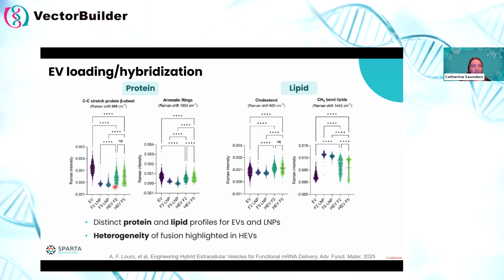This is confirmed looking at a couple of different protein signals, and also when looking at the lipid signals, where you see the inverse. The EVs score lower on their lipid profiles, but the LNPs, of course, score very highly. Again, there's a real spread in terms of the hybrids in this lipid signal, showing that there was some successful hybridization, but there's quite a lot of heterogeneity in these samples that were made.